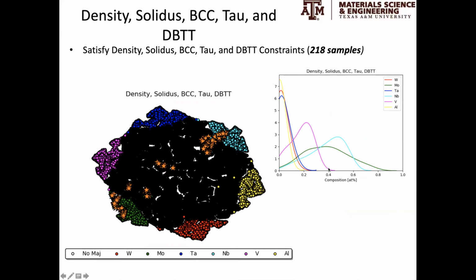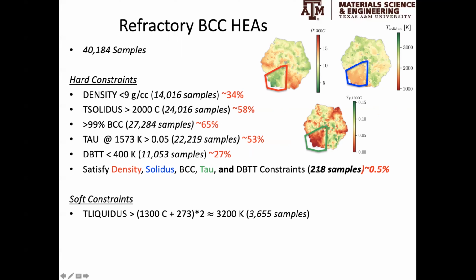So when we consider all these different constraints, despite the fact that a lot of these alloys comply with each one individually, when we put them together, we find that the intersection of these different constraint boundaries results in only 0.5% of the total space being satisfied.